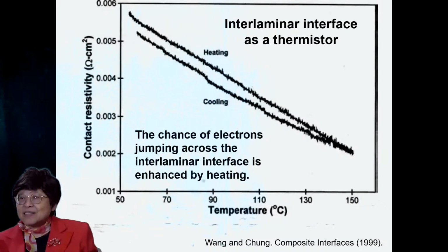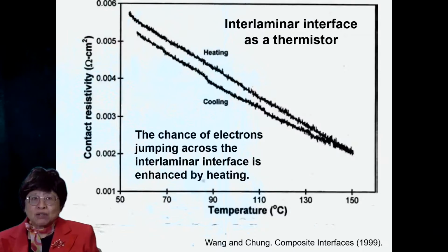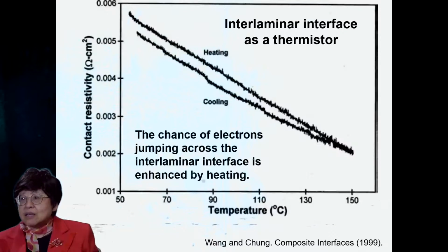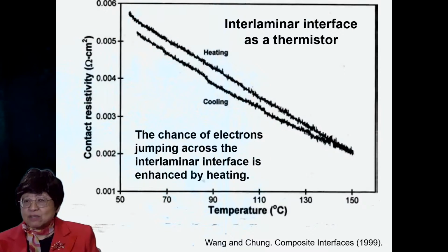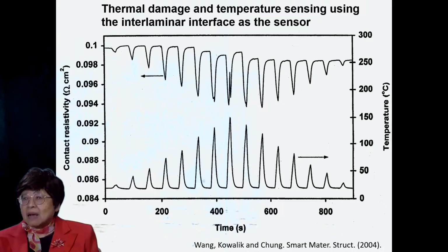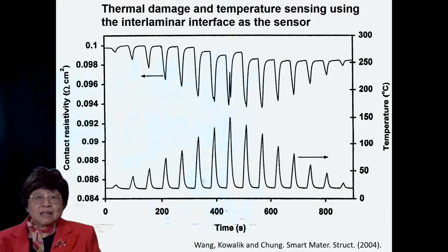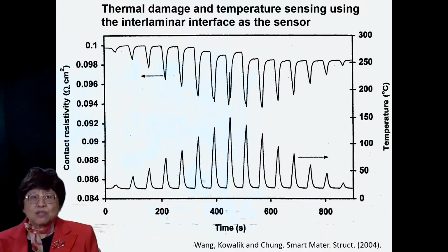In addition, this interlaminar interface can serve as a thermistor, that is, a temperature measuring device based on the resistance varying with the temperature. So this is the contact resistivity versus temperature. Upon heating, it decreases because the chance of electrons jumping across the interlaminar interface is enhanced by the heating. Not only detecting the temperature, the contact resistivity responds to the thermal damage of that interface.